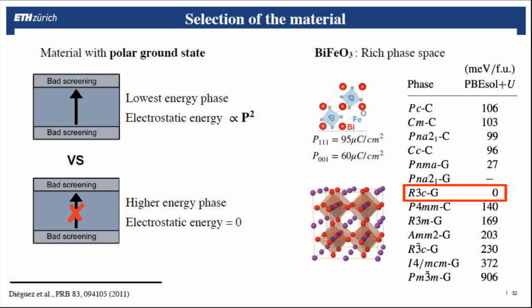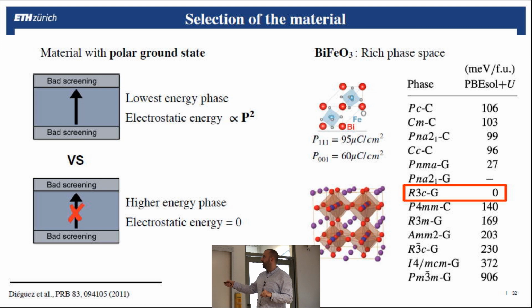But what is interesting is that these are also numerical results. If you consider this size of unit cell, you can actually find all these possibilities and the energy here, so that's the ground state, this is the 0 energy, and then you can find different other phases that are not so far away from the ground state. So that gives a good hope that one can find a higher energy phase but not too high, and that would be better than having this large electrostatic cost.